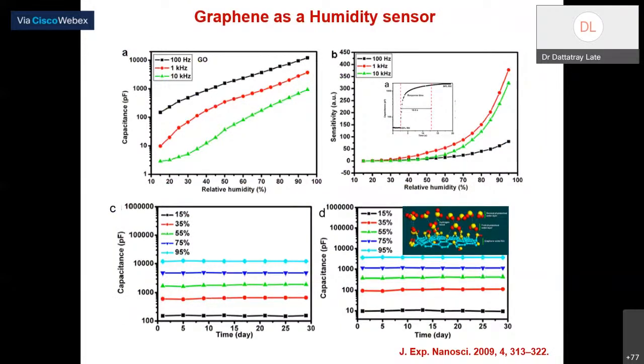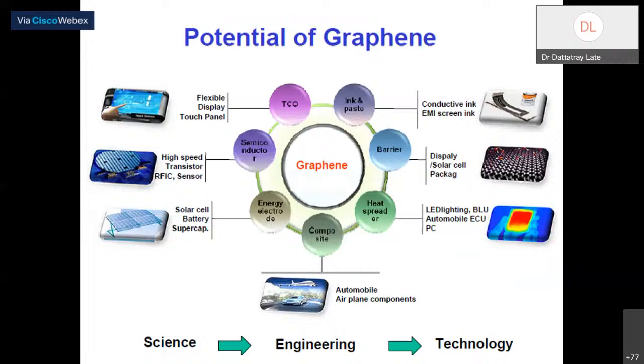We also tested these kinds of devices for long-term stability. We found that the devices are stable up to 30 days, which gives very stable device performance, and they can be used for humidity sensing applications. Okay, so graphene has a lot of potential.